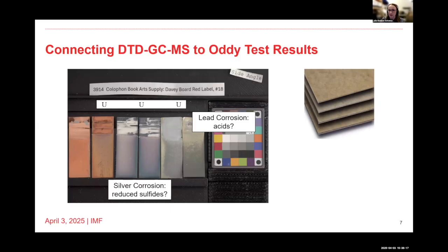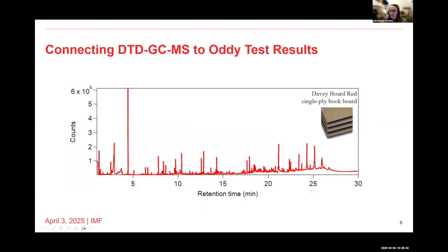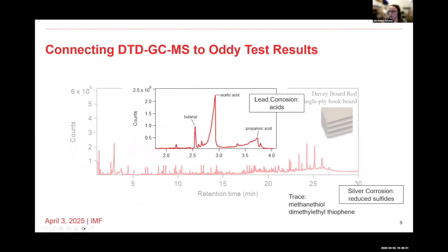Based on past work and literature, as Devin mentioned earlier, it can be pretty extreme corrosion on lead when organic acids, acetic acid, formic acid, and others are present. And we've also, as a community for a while, known that silver corrosion, specifically this purple silver tarnish that you can see in the image, can be related to the presence of reduced sulfides. And so again, here's that GC chromatogram, and through the analytical process of this data, if you zoom into the first 4 minutes of the GC chromatogram, you can see peaks that have been assigned to acetic acid here. And in the larger chromatogram, that's the largest peak in the chromatogram. So there's quite a bit of acid here. And then you can also see other acids, and I'm showing here propanoic acid, which is also present. So we can link that lead corrosion to those organic acids.